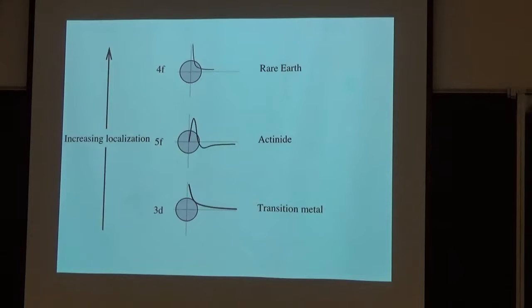But inside metals, at least in elemental metals, the most strongly interacting electrons are those that are inside the core states of the D shell or the F shell. The most localized D shells are the 3D shells, and that's because they have no node in their spatial wave function. They're basically hydrogenic wave functions, the 3D electrons. And that's because when n is equal to L plus 1, you get a hydrogenic wave function. So if you now go up to the F shells, then 4F also has a hydrogenic wave function and drops even further inside the outer shell of the inner gas shell.